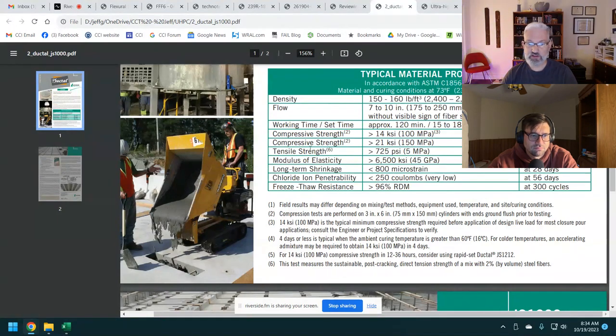All right. So here's your compressive strength. KSI is just K for kilo, like 1,000, so it just means 1,000 PSI. So 21,000, 22,000 PSI at 28 days. And they also show that this particular product, when cured correctly, reaches greater than 14,000 PSI at 4 days. So very high compressive strength. Remember that. Compressive strength. Nowhere on here is flexural strength.